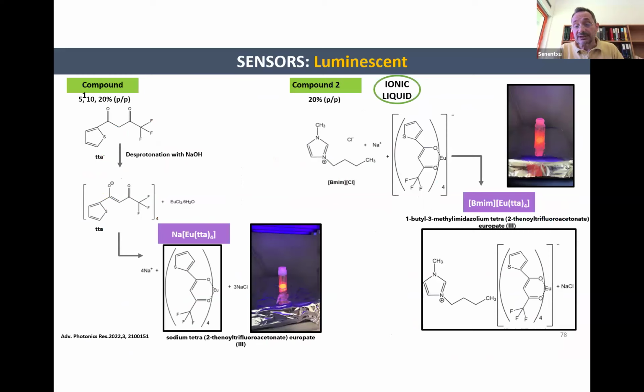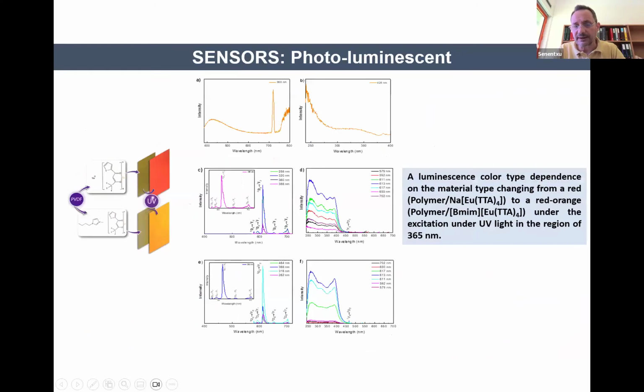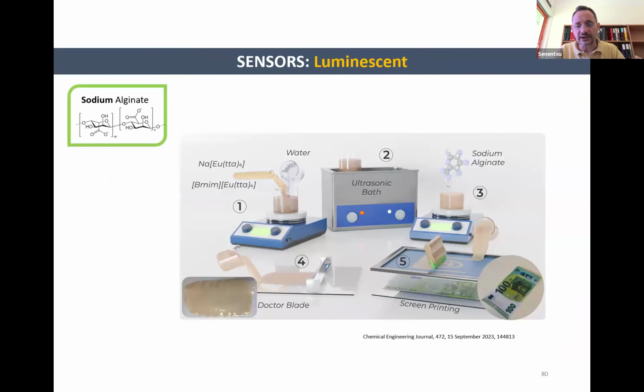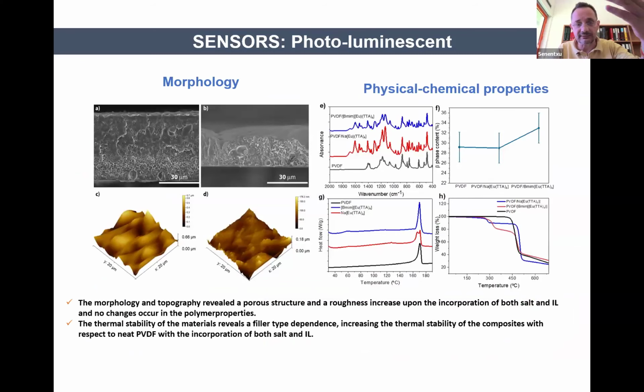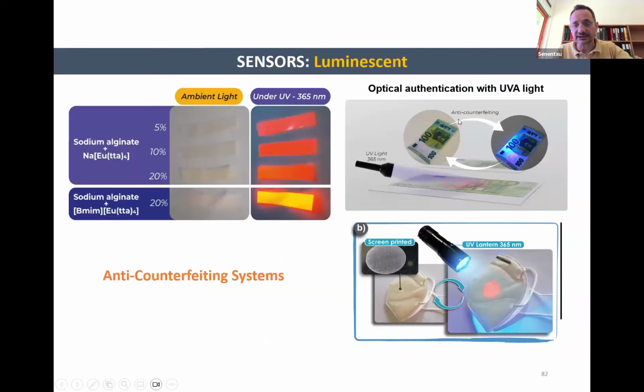Photoluminescence, to give the same example, because it is right. Again, basically, most of the times in the work that we are doing, we are using basically the same cation, but we are changing the anion with a luminescent particle. You can tune there, and this is based on alginate. Again, we make the interaction with the polymer, the stability over time, and you can have this beautiful luminescence particle that you can use for anti-counterfeiting, for example.